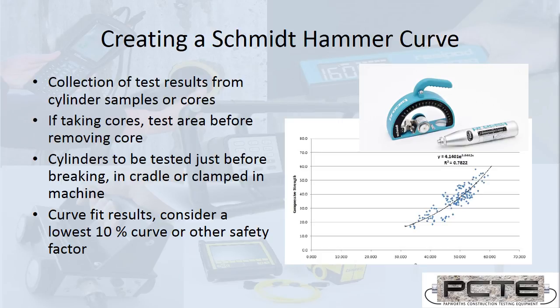With cylinders, they do need to be held securely. If the sample slips or moves under the strike of the hammer, it's going to report a lower rebound value. So in a cradle, or commonly, a little bit of pressure can be applied in the machine to hold it firmly, the sample test taken, and then the compressive strength test completed.